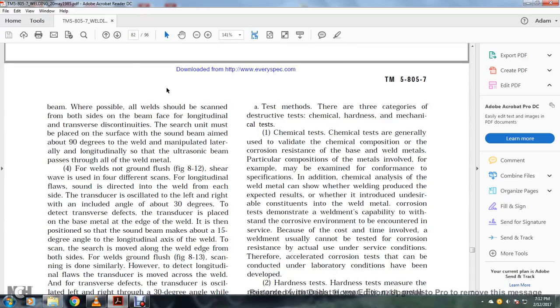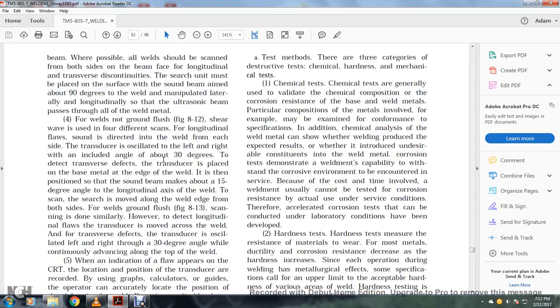Angle beam. Whenever possible, all welds should be scanned from both sides of the weld with the beam faced to detect longitudinal and transverse discontinuities. The search unit must be placed on the surface of the weld with the sound beam aimed at 90 degrees to the weld and manipulated laterally and longitudinally so the ultrasonic beam passes through all the welded metal of the material. Four. For welds that are not ground flush, as in figure 8.12, with the shear wave, use four different scans. For longitudinal flaws, sound is directed at the weld from each side of the weld. The transducers oscillate from left to right through an included angle of about 30 degrees to detect transverse defects.